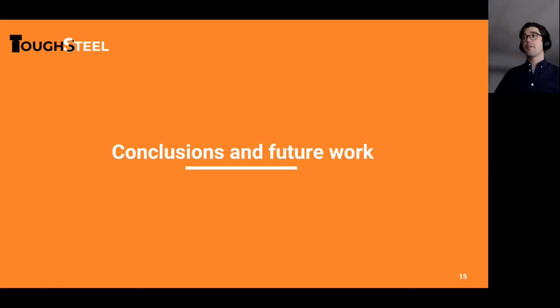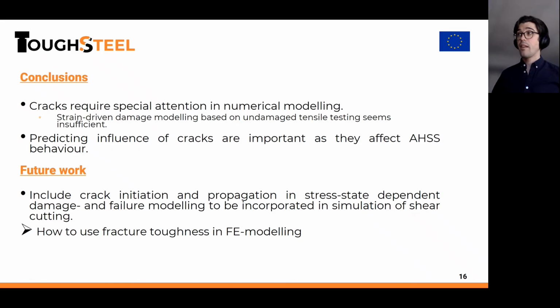So to sum this up, I will state some conclusions from this presentation and thoughts about future work. And I think that I made my point at least. If you model processes involving cracks and crack propagation, you need to take them into special consideration. The strain-driven ductile damage modeling presented today is most likely insufficient for this. And if cracks are not considered, there's an imminent risk that your modeling accuracy will diverge as cracks appear to affect the advanced high-strength steel behavior.